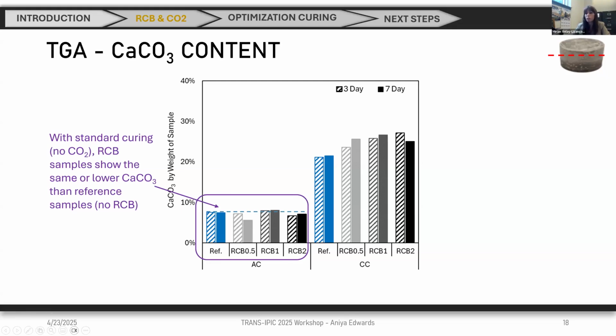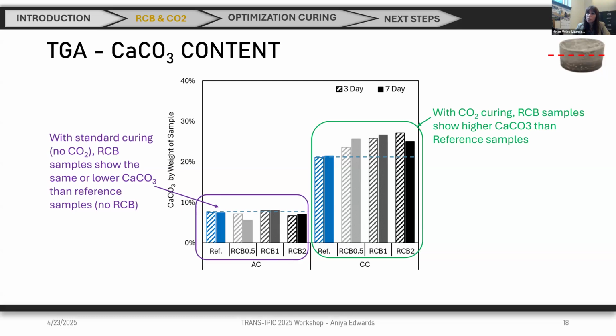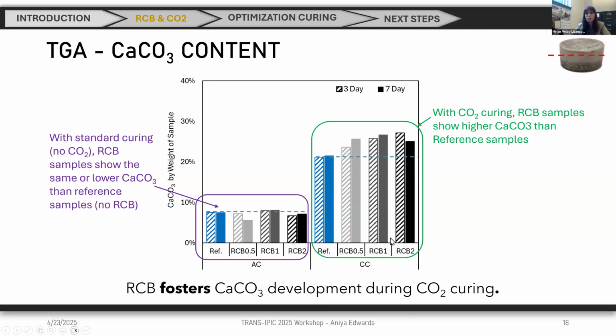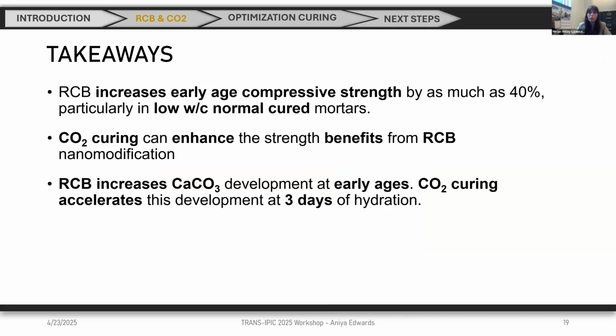However, when we check the results of calcium carbonate content with CO2 curing, we will see that when you have recovered carbon black, the amount of calcium carbonate is greater than in the reference one. All of them are CO2 cured. And therefore, what we are seeing is that the presence of recovered carbon black fosters the calcium carbonate development in presence of CO2 curing. That's relevant, especially because we observe that that's not related to increasing the carbonation depth, it's more related to the amount of carbonation on the surface layer that you will see later on in the next part.